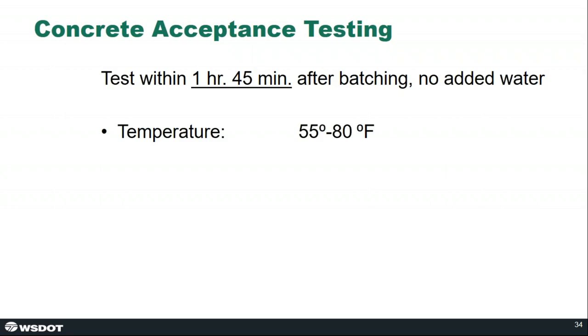So we do test for temperature, and we specify a range between 55 and 80 degrees. I mentioned earlier we had moved to a 75 degree maximum. We were finding that that was actually pretty difficult for contractors to achieve on a routine basis. So we did give a little ground there and raise that temperature to 80 degrees, but that's still less than the 90 degree limit we had had previously.